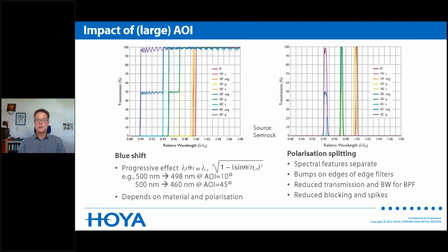Thin film interference filters have a natural property, that is the sensitivity to angle of incidence, because if you do not have your nominal angle, the spectral properties will shift towards shorter wavelengths because the path length of the optical ray changes in the filter. So you can see on the left-hand side a plot for 0, 10, 30, and 45 degree angle of incidence.